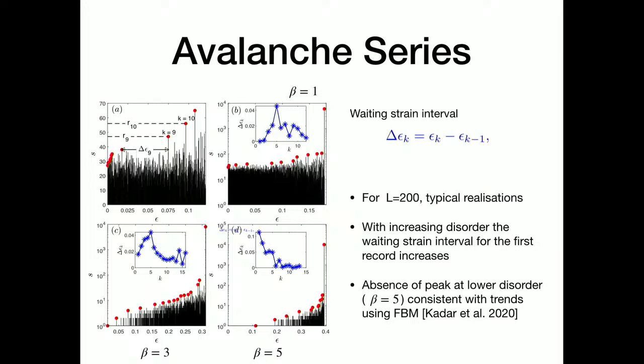Anyhow, some interesting observations in terms of waiting strain interval: for the first record, as we increase disorder, this is the lowest disorder. The lowest disorder has a very high first record, and then as the records are made, it has a kind of decay, or the waiting time interval keeps on reducing, and there is a sort of acceleration towards the final failure. So this is the waiting strain interval.